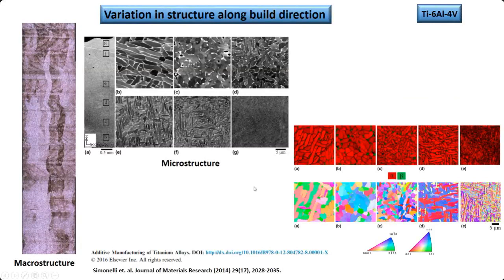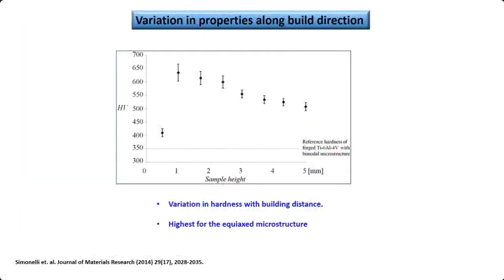This has a huge role to play when we talk about strength and hardness, because the microstructural size is inversely related to the strength of the material. You might be familiar with the Hall-Petch relation, which says that the yield strength of the material is inversely related to the square root of the grain size, lathe size, or any kind of microstructural size. So as we have finer and finer microstructure, we have higher and higher hardness or strength.